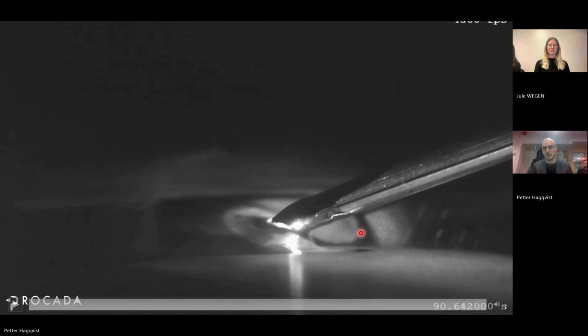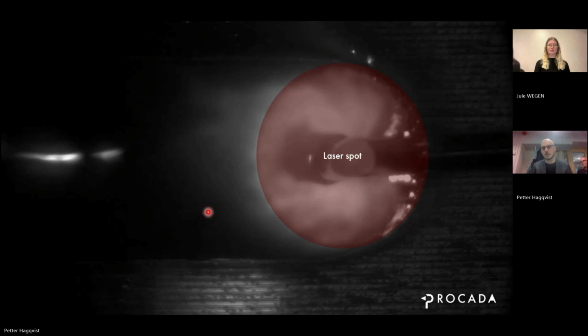if I can get my pointer here. This area is illuminated by the laser, the light area. The dark area underneath the wire is not illuminated by the laser. So in this picture, it corresponds to this area where the laser is shading the melt pool. And you can see these shapes here, which we call a horseshoe. It doesn't really look like a horseshoe, but there's an indentation in the melt pool here where we don't have as much molten material. This is important for later.